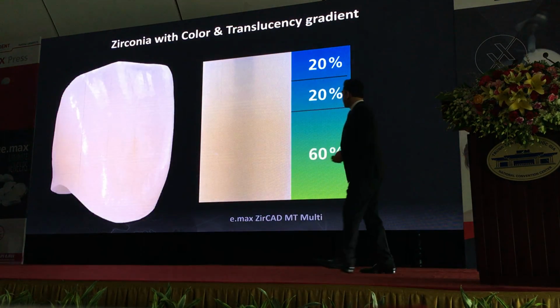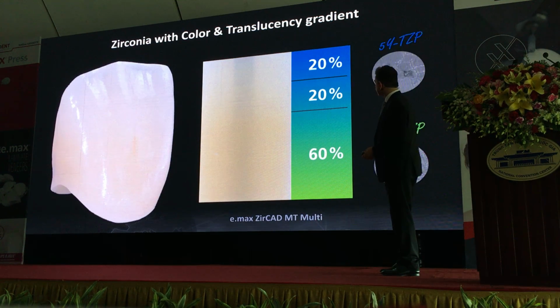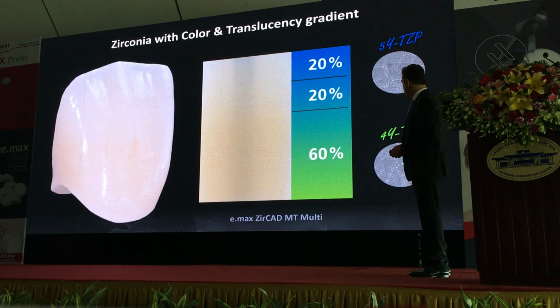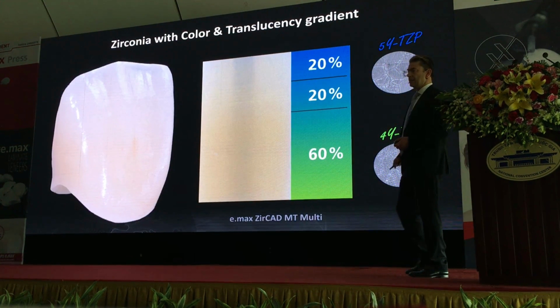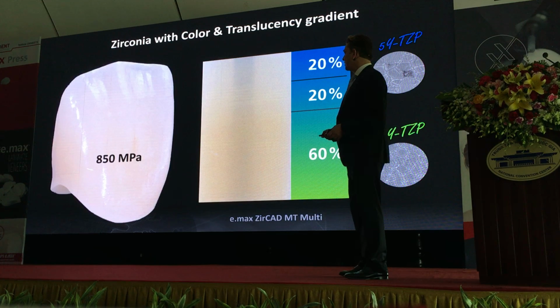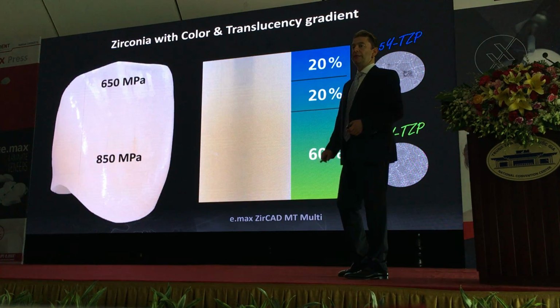So you can see when you mill a crown out of this multi MT material, you have a color gradient. You can see it's more opaque in the cervical area and more translucent in the incisal edge. Different raw powders: for the cervical one, we have the 4YZ, and for the incisal one, where we need the translucency, we have a 5YZ zirconia, which means that we have 850 megapascals in the cervical and 650 megapascals on the incisal edge.